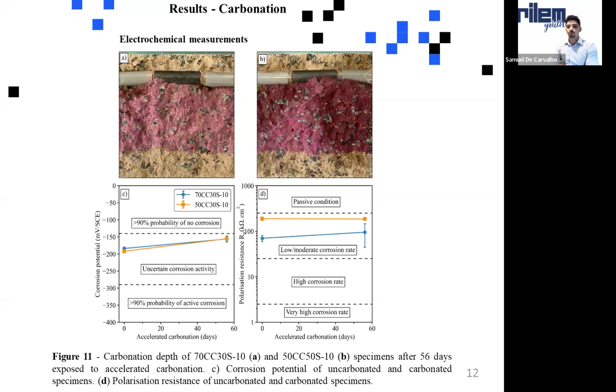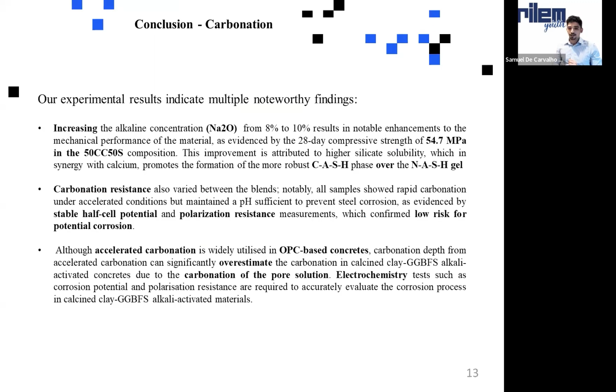As I showed you before, this area that shows carbonated, you measured the pH before, and it is still around 10.8 or something like that for both of the experiments. On A, you have a specimen with 70% of calcined clay, and this is 50% of calcined clay, 50% of GGBFS. The polarization resistance also shows a really low to moderate corrosion rate probability on both of the samples. So based on that, you draw some conclusions on the carbonation.